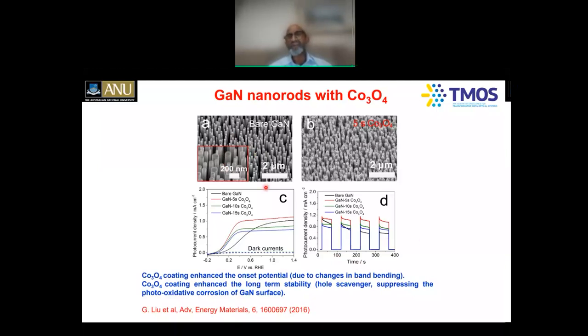So we had to coat these gallium nitride nanorods with cobalt oxide, using the flame pyrolysis technique in Professor Antonio Tricoli's group in engineering at ANU. We were able to show that if you coat this thin layer of cobalt oxide, you get very stable structures, which look very promising. But gallium nitride itself is not the best material because it has too large a band gap. That means it doesn't absorb visible light. We're exploring a wide variety of materials, like indium phosphide nanowires and others, to see if we can create stable, efficient nanostructures for the most efficient hydrogen generation process.